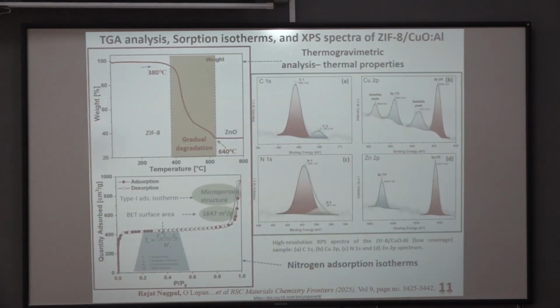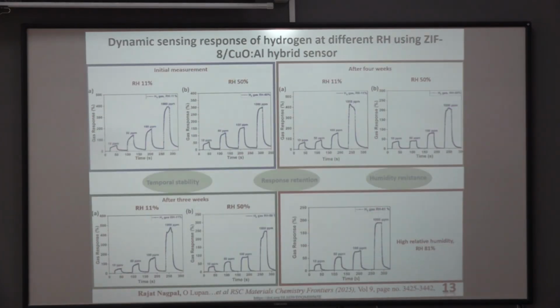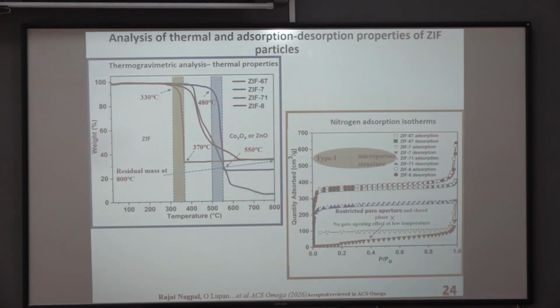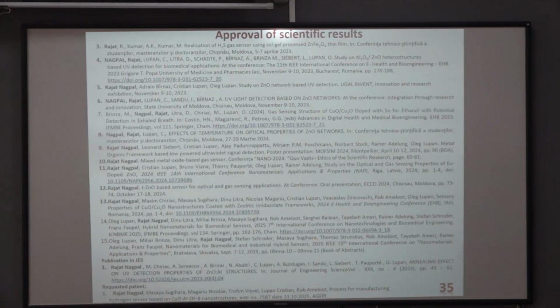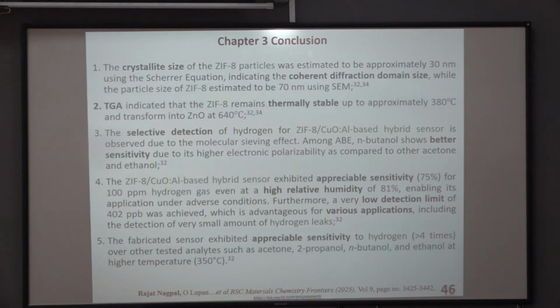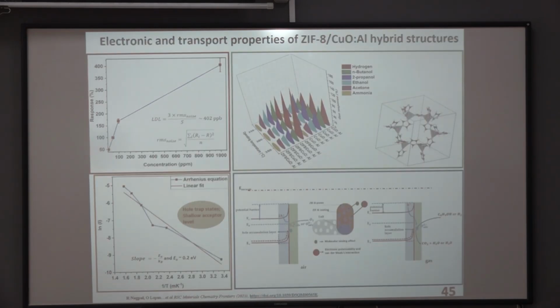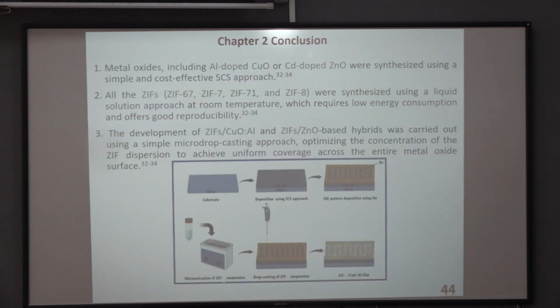Yeah, for example, if you go to the supplementary slides, here we can see, in the case of the ZIF-based hybrids, we tried using an Arrhenius plot to understand what possible defects are present. What we got from this Arrhenius plot is that this is due to hole trap states, whose activation energy comes out to be around 0.2 electron volt. So the slight aberration at high temperatures could be attributed to this defect, or maybe some other possibilities. But they are very small. Okay, thank you. Next question.